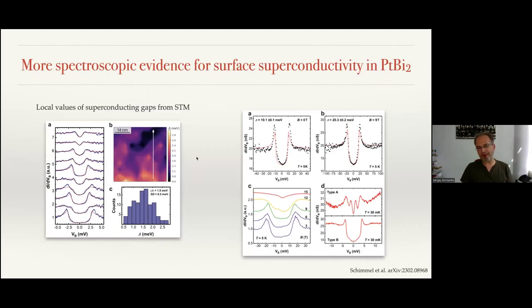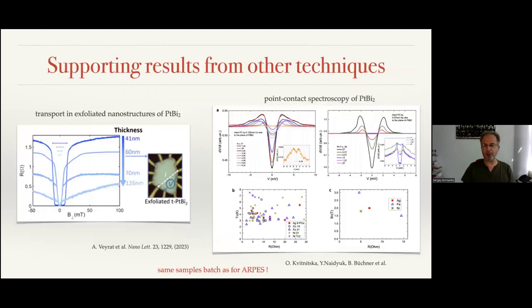The value of the superconducting gap is in remarkable agreement with the STM data. We have this data from our colleagues. They showed that the gap is inhomogeneous on the surface of the sample, but the average is 1.5 millielectron volts. This is exactly what I just showed. And there is typical behavior with magnetic field, unambiguously showing that we deal with surface superconductivity. This is also confirmed by other methods.